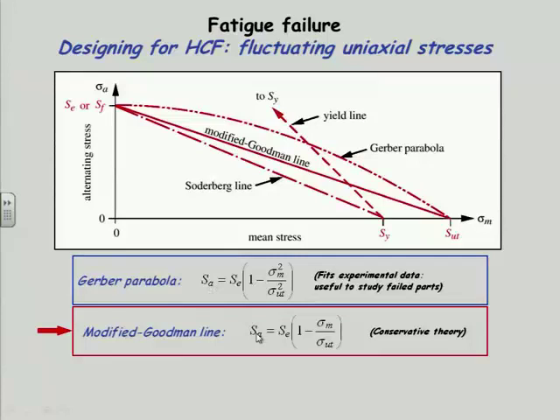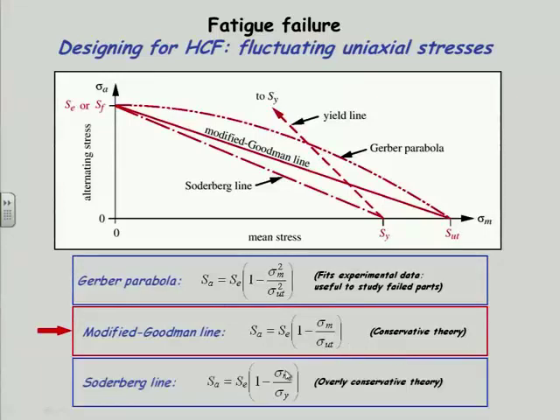That's a stand-in for either S sub F or S sub E. It's just a generalized alternating strength. Endurance limit times 1 minus sigma m squared. Now sigma m would be your applied stress level in the mean direction, divided by sigma ut squared. That's the ultimate tensile strength. And that fits the experimental data very well. Goodman line, it's a linear line, so it's the first power, similar expression, 1 minus sigma m over sigma ut. And the Soderberg line puts sigma y in instead of sigma ut.